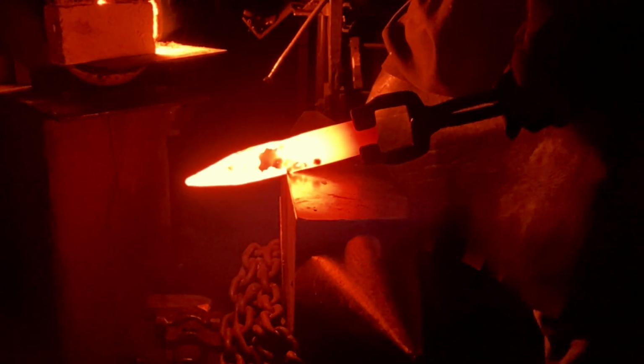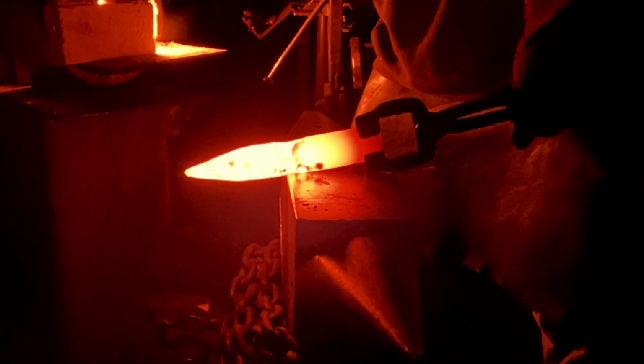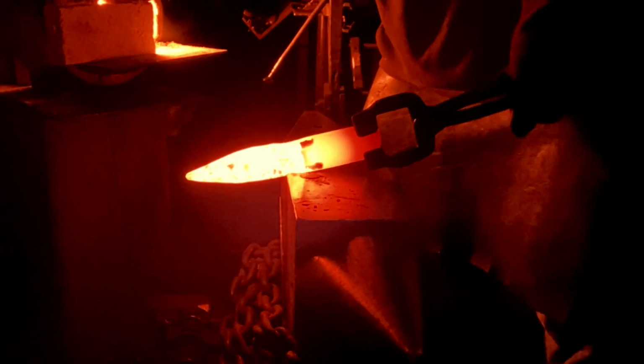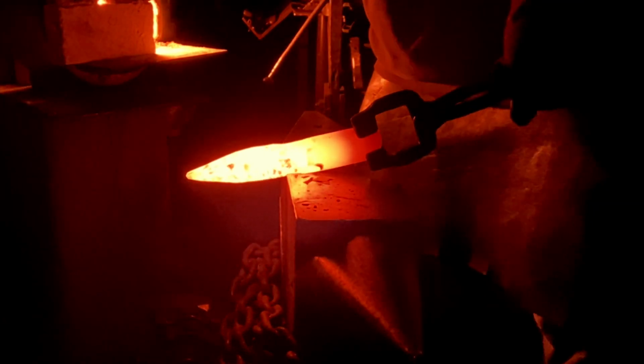Another thing worth mentioning is Wootz benefits from forging. It's basically where the pattern comes to life. Typically the pattern improves with forging cycles, and forging your bevels will help align those dendritic sheets with the surface. So if you're somebody that likes to forge your blades to shape like I do, this is some really awesome material to work with.